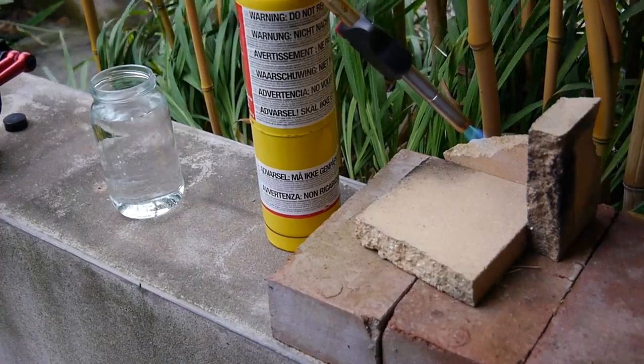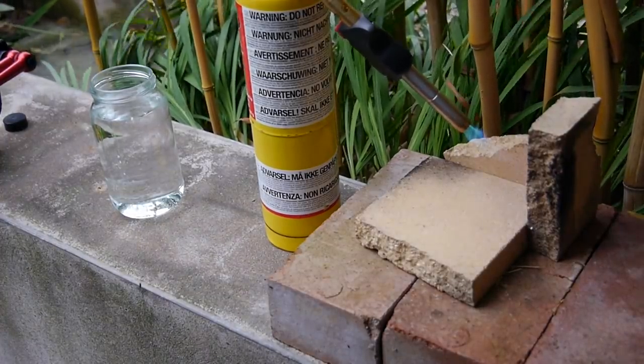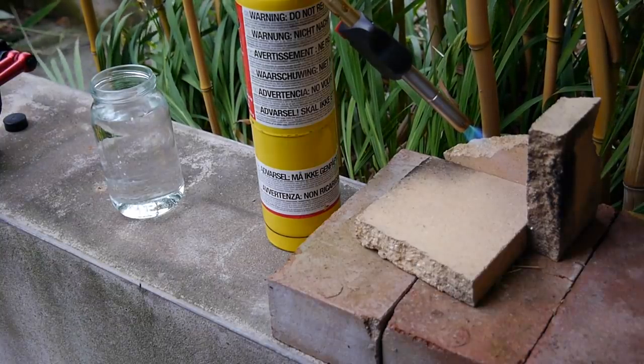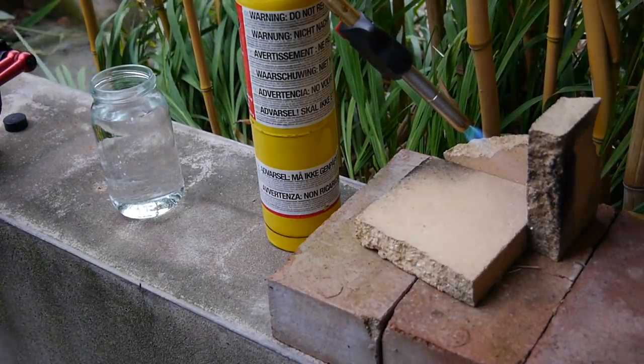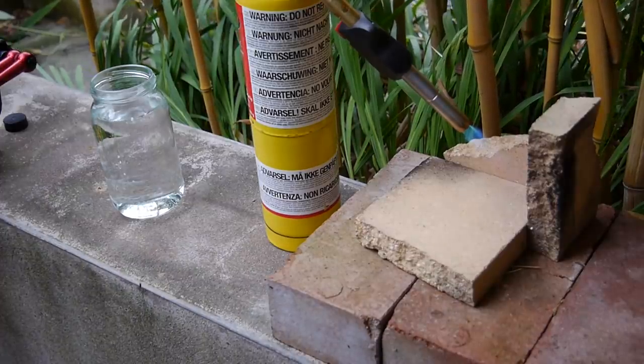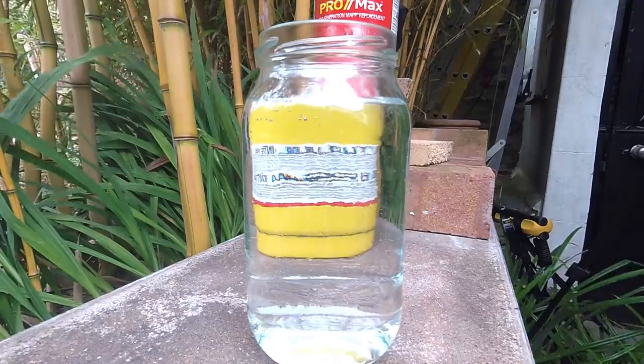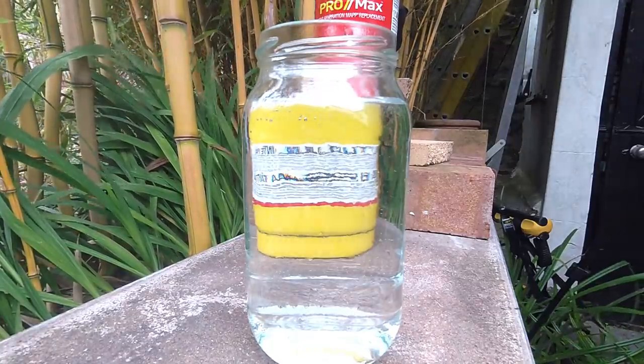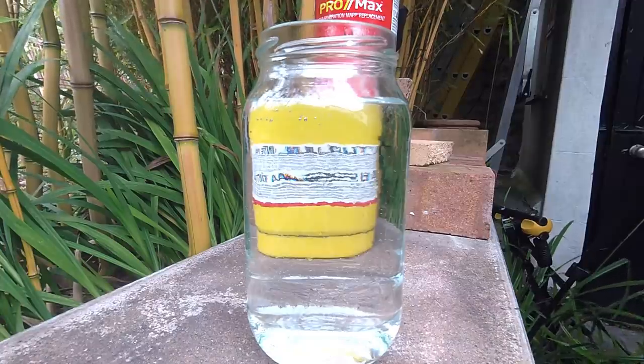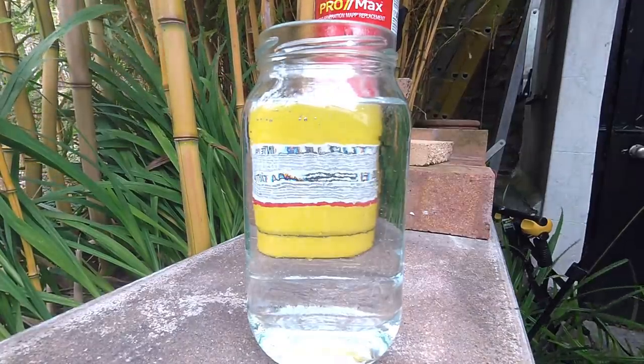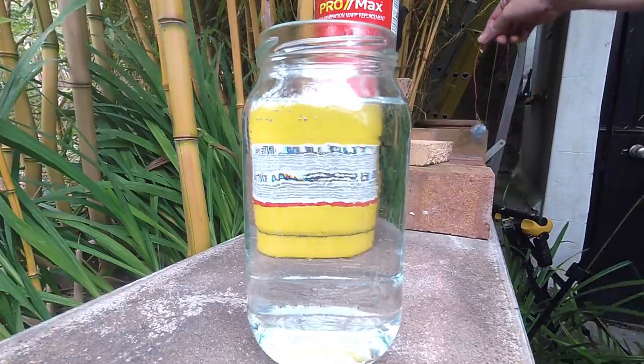I pre-warmed the hearth while I was preparing the die for hardening to try and get more even heating. The burner uses MAP Pro Gas, which burns in air a few hundred degrees hotter than propane. For very small parts, the silver steel datasheet recommends quenching in clean water, which has the advantage of being less messy than oil. Some metal workers recommend brine to reduce bubbles, but I'm going to wait until I have something that's easier to remake before experimenting too much.